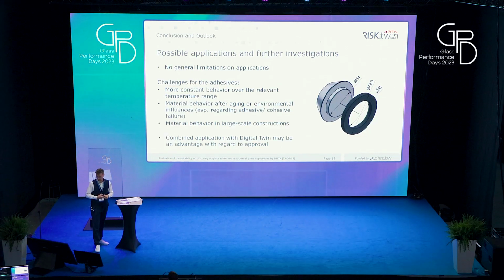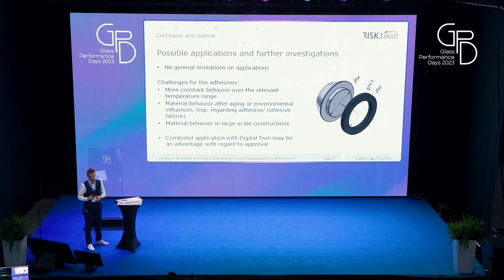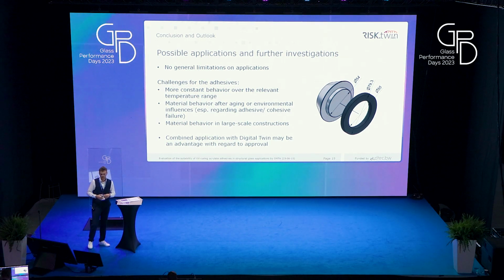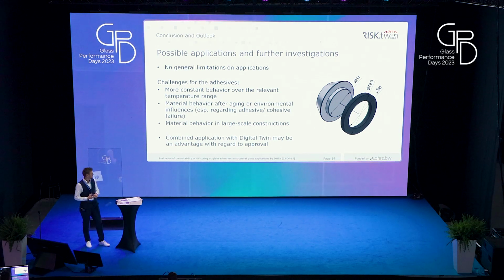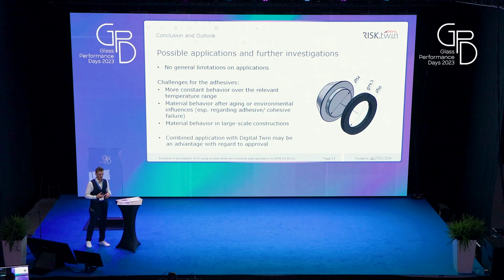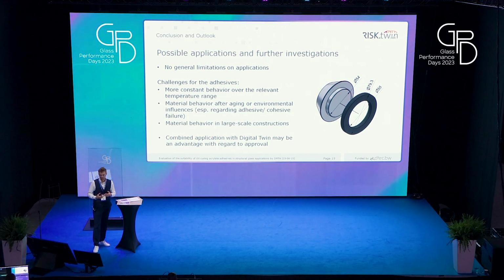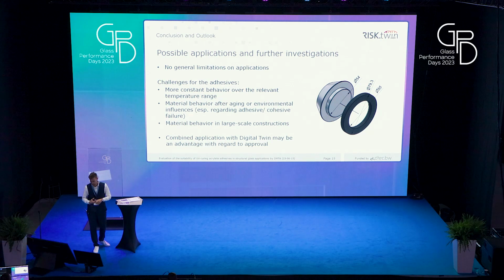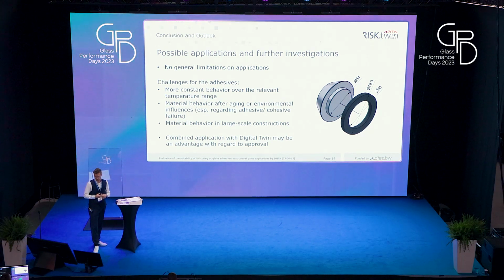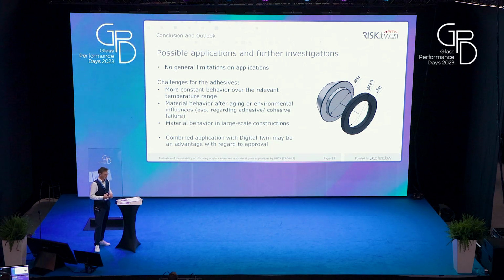Now, to close my presentation, I will have a short outlook. So we could actually not figure out any general limitation of UV curing acrylate adhesives, but there are, of course, some challenges which we need to face. At first, a more constant behavior over the whole temperature range would be desirable, and we haven't done any aging tests on the materials so far. So especially, we need this to investigate in glass to steel connections, because then adhesive failure might occur, which we don't have, of course, in material tests on the bulk material.